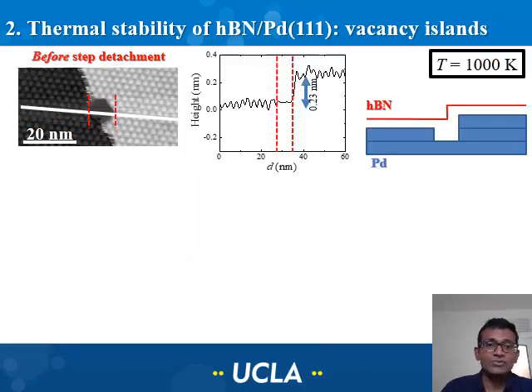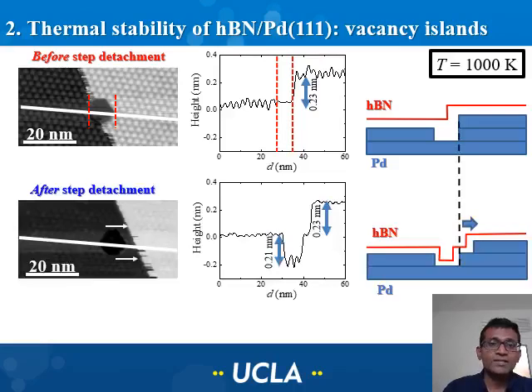What we observe when we measure the step heights when it's pinned and when it's detached is that when it's pinned, we measure a step height that corresponds to a monolayer of palladium, implying that the hexagonal boron nitride is taut. It's as if you have a plastic wrapper that is tight across a bowl, and you do not see the actual depth